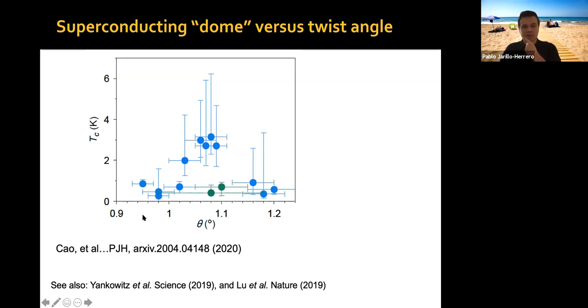Jeannie Lau showed some evidence for superconducting devices for even 0.93 degrees twist angles the other day. And the maximum is about 1.2 degrees that we have seen. So these boundaries may extend a little bit further, but it's quite clear that it has to do with the vicinity of about 1.1 degrees. And the maximum seems to be there between 1.05 and 1.1 degrees for most people.